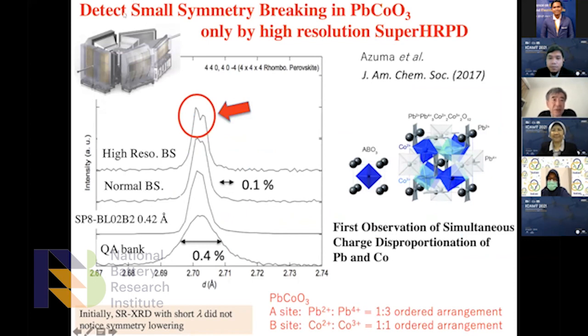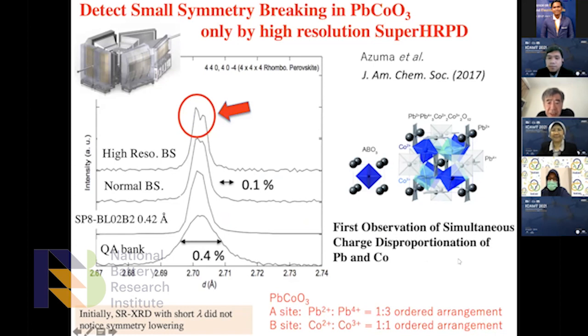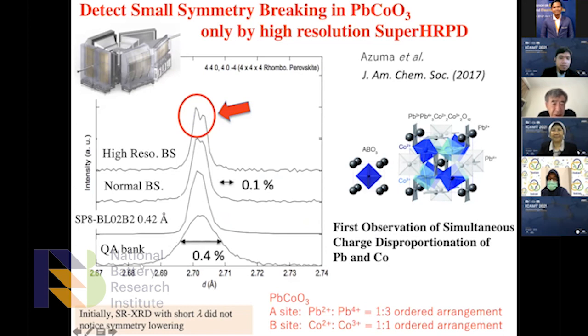One example is detecting small symmetry breaking in lead cobalt oxide, only possible with a high resolution instrument. Here, the d-spacing shows splitting of a peak — the first evidence of simultaneous charge disproportionation of lead and cobalt. With a normal instrument, such as Spring-8 with a wavelength of 0.42 Å, the peak is a little broad, similar to ordinary laboratory X-ray or neutron diffraction. High resolution is essentially necessary to detect this kind of splitting.